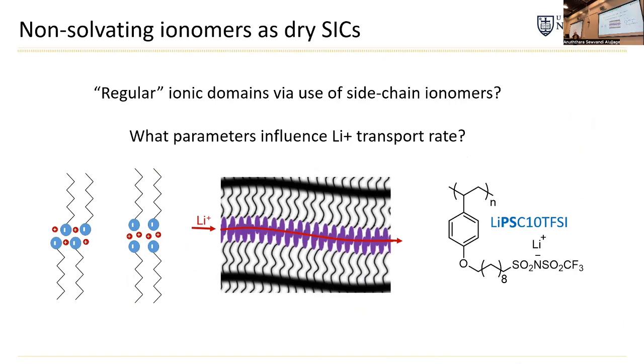And then there's another class of polymers that people have been studying more recently, in my group as well, where the polymer itself doesn't have any polar component. And so the ions cluster all together. It's more like the local anion or cation environment would be if you had a dry surfactant, basically. What we're trying to understand in these studies is whether you can get decoupled lithium ion motion. If you can get the lithium to move, then it can decouple from the segmental relaxation of the plastic and actually pop.